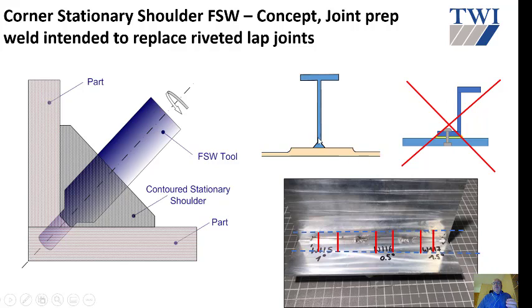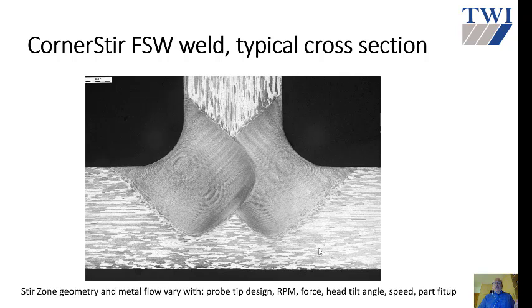So, going back to the process, the joint preparation is quite unique. The 7050 part is prepared in an elephant foot configuration. There's no filler wire being brought in, so in order to avoid undercutting, this particular geometry has to be pushed down really hard with a fixture, and the aircraft skin is actually thickened a little bit in the area where the ribs come in. Yet it's still only 2.8 millimeters in this area. So you see some fillet welds here. You will see how this looks in a traditional one. This is a generic picture showing the two passes, one from the right, one from the left.